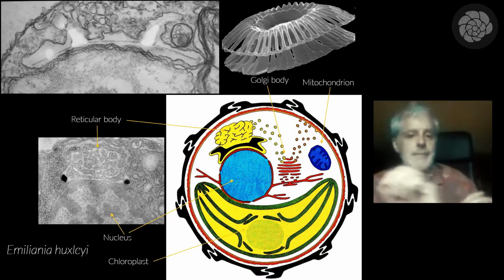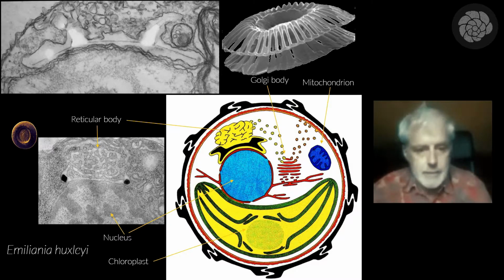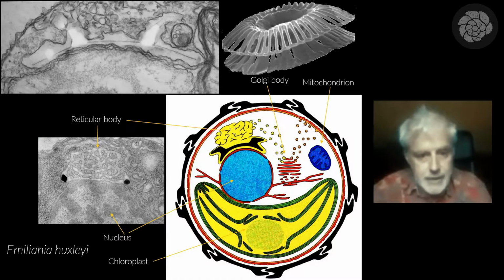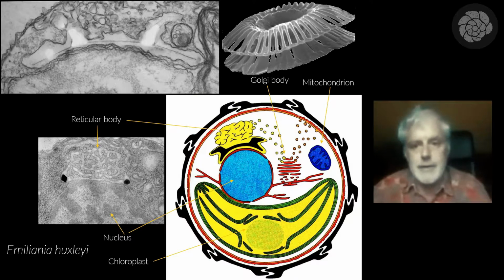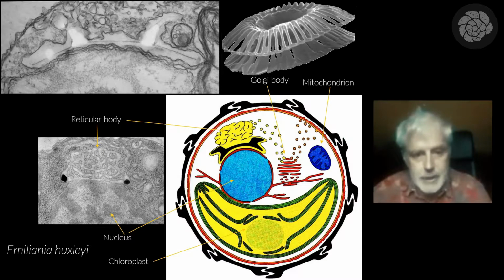However, the cool part, in terms of how those coccoliths are forming, is that it's a two-phase process. First, they nucleate. There's the initial phase of calcite nucleation, where very simple little rhombohedral crystals form. You can see them here. This is in Emiliania huxleyi as a sketch section, and then these are transmission electron micrographs, thin sections, showing it forming, then getting larger.